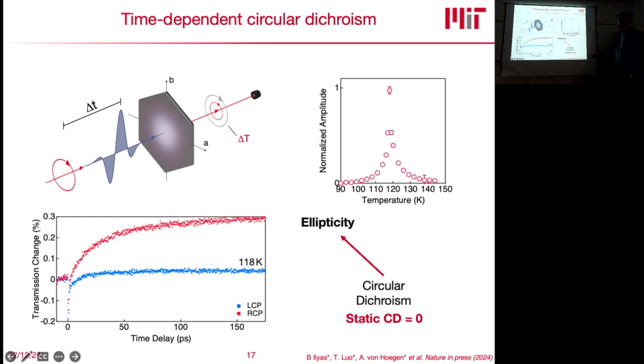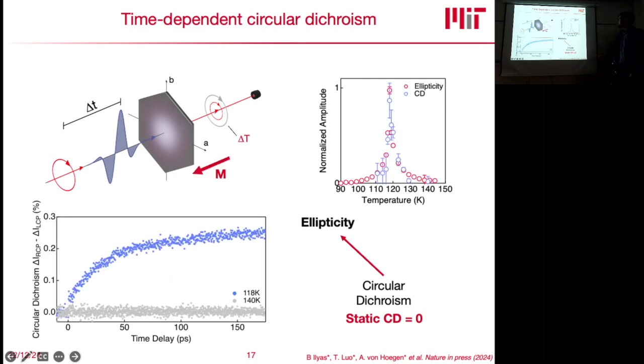So if you send in left circular polarized light, you get a small change, and basically not a long-lived change. However, if you send in right-hand circular polarized light, after the terahertz excitation hits here, you start seeing a dramatic change in the transmission. And if you now map the temperature dependence of the circular dichroism, which is unfortunately a much noisier measurement compared to our polarization rotation or ellipticity measurement, we find a very similar temperature dependence compared to the ellipticity measurement, which strongly suggests that the ellipticity change in this material and the circular dichroism come from the same physical effect.